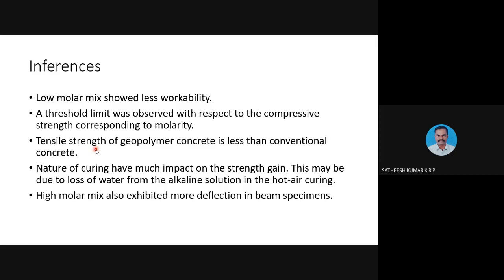And as I have mentioned earlier, the tensile strength of the geopolymer concrete is found to be much less than that of the conventional concrete. We were trying to attain 20 megapascal as the compressive strength, but the split tensile strength was only around 1.8 megapascals.